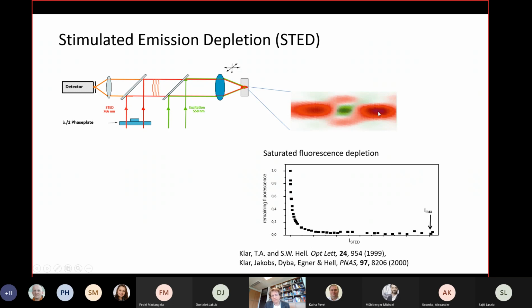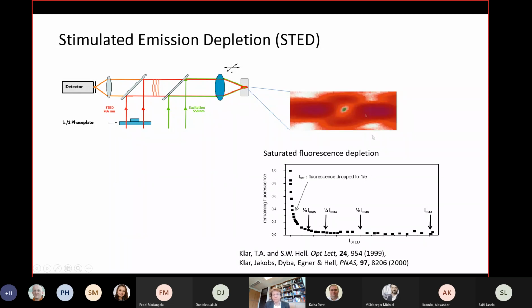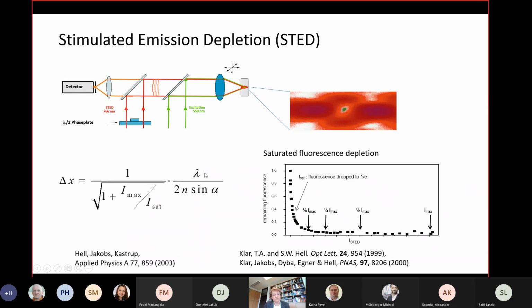And at the maximum of the intensity, you suppress all the fluorescence. At half of the intensity, you suppress all the fluorescence. At a quarter, at an eighth of the intensity, you suppress almost all the fluorescence. So if you fold this intensity pattern of the red point spread function with this fluorescence suppression ability, you blow it up, and you immediately see that the remaining center where you still have active fluorophores becomes very tiny, and one can quantify that.